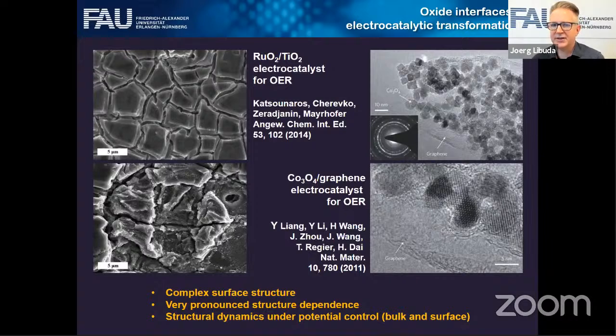The other example that you see here is a cobalt oxide based nanomaterial, cobalt oxide nanoparticles on a carbon support, again a complex nanostructured surface. So what is the issue here? First of all, as you can see, these surfaces are not simple. They expose very different structures to the electrolyte, and we have to understand what these structures are. Very often the surface structure under reaction condition is not understood. We would need to know where the atoms are in any of these structures that we see there.